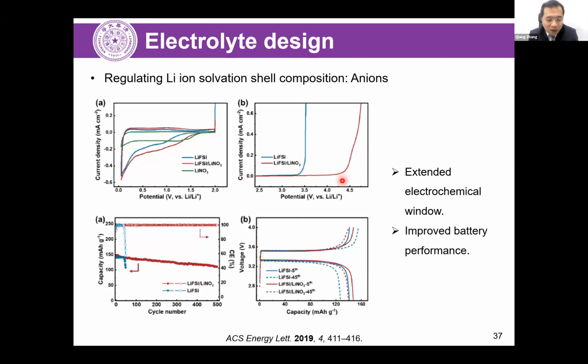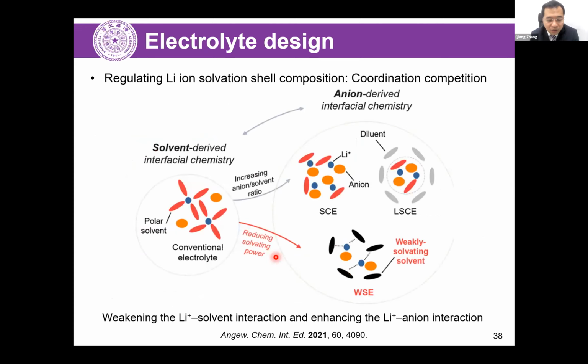And once we compare the cycle life, it is found that the regulation of the solvation complex structure can regulate the protection of the SEI, and this gives the cell quite a long cycle life as well as stable polarization over the whole life. So this is quite important to provide the feasibility of cycling the cell with a long cycle life.